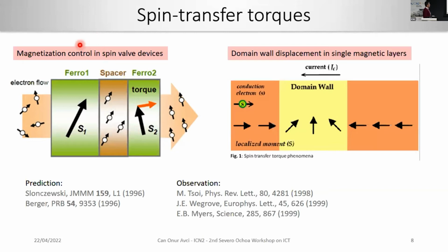And these other ways of using the spin polarized current is in a single ferromagnetic layer if you have a domain wall. So if you have a domain wall, then the conduction electron will conform to the local magnetic moments in the material, therefore, when it passes through this domain wall, it will also exert a torque on the spin of the domain wall, and it will move it eventually after a certain threshold current.